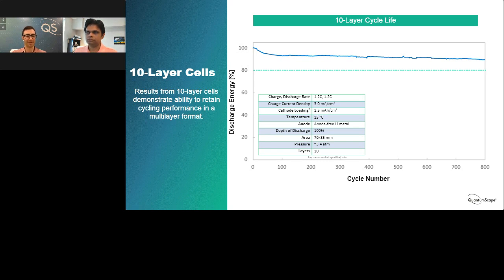Maybe one other point to note here is this was tested at a pressure of 3.4 atmospheres, as have most of the other cells that we've presented on. This is a relatively modest pressure. For reference, lithium-ion cells are at something like 0.5 to 1 atmosphere, and this helps because as lithium moves in the battery, layers expand and contract, which is called swelling or breathing in the battery. And a modest pressure helps keep all the components next to each other and keep the resistance low.